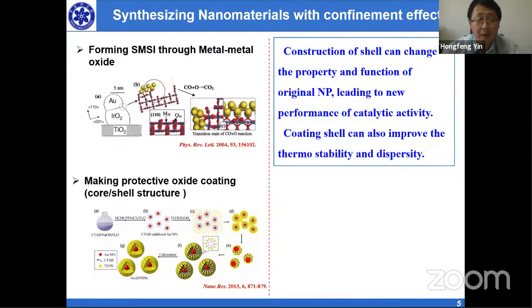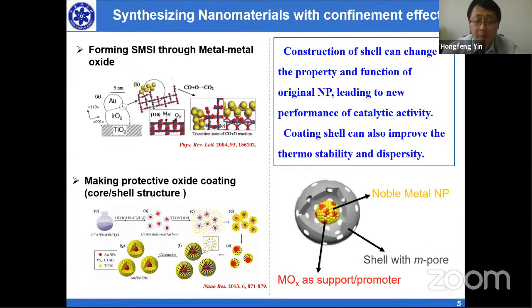So by combining these two, forming strong metal support interaction and making a core-shell structure, that's the target we are trying to do. For example, this is a core-shell structure. We have a noble metal nanoparticle as a core, and we have a metal oxide as support and promoter. Metal oxide has a pretty good interaction with the noble metal, and it can also work as a promoter. Then this structure has a shell with mesopores. The shell can protect the noble metal from aggregation. With mesopores, it will allow the substrate to transfer in and the product out.